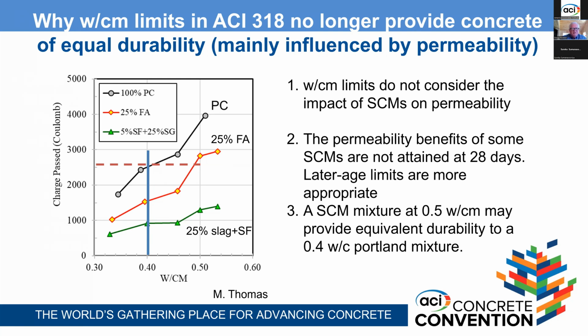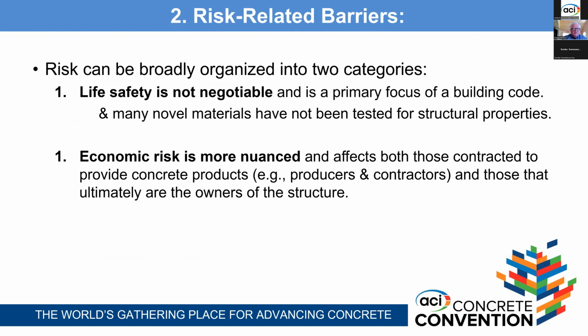So they'd all meet the C2 spec in 318 if they were 5,000 PSI and met the water binder ratio. But they all have completely different durabilities in terms of how long they're going to last in chloride exposure. We're talking about decades of different performance based on the different penetration resistance of those concretes, but they're all equal under the code at present, because there's no performance measure. So that's something we're trying to address, but it's an uphill battle.